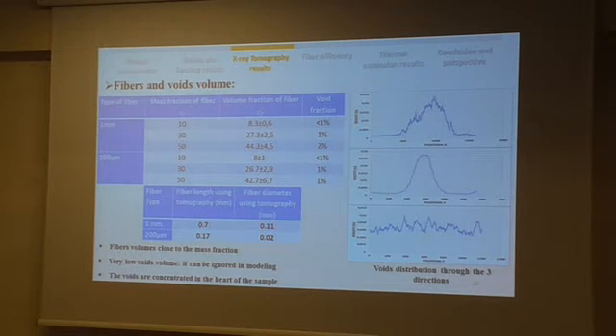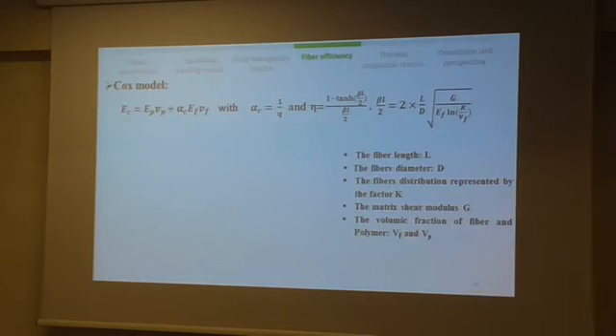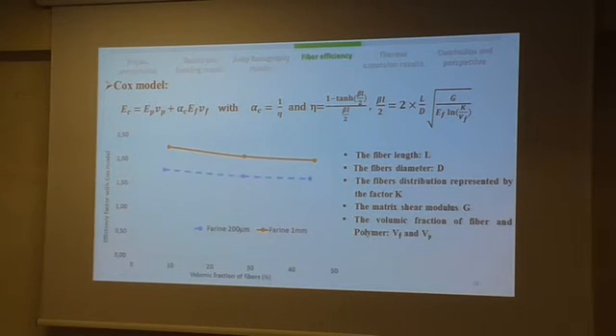So using those different parameters, we were able to inject those parameters in an analytic model to calculate the efficiency of the fibers. So in order to do that, we used a simple model established from the law of mixture, which is the Cox model. So in this model, we are searching for alpha, which is considered like fiber efficiency. Alpha here is calculated using all the parameters determined using the X-ray tomography technique. So we found that the efficiency of the fiber decreases with the increase in fiber rate, but it tends to be constant.